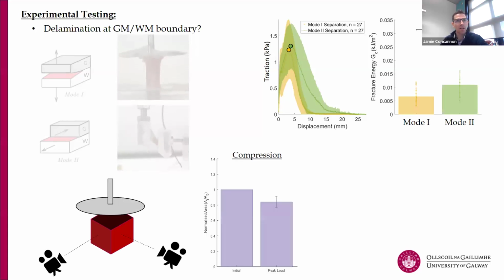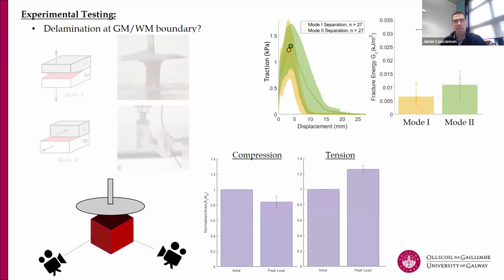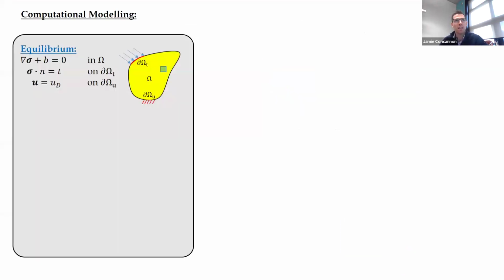And the last thing we started to look at in terms of the experimental data was the volumetric effects, or the compressibility effects. Again, we did these experiments and set up two different orthogonal cameras, and we're seeing that there is significant compressibility across tension and compression. So there's a lot of experimental data there, and we now need to shift gears a little bit towards how we computationally model this.